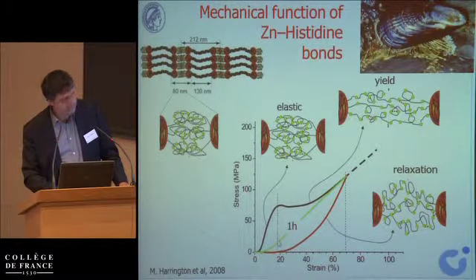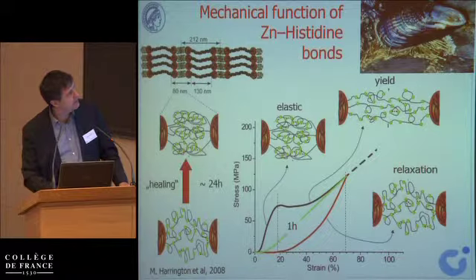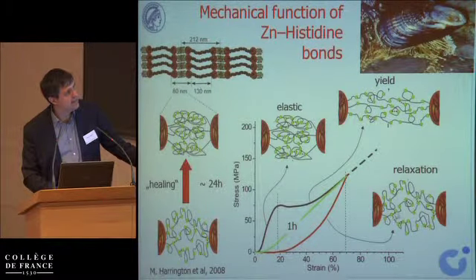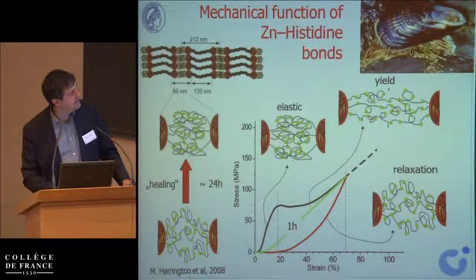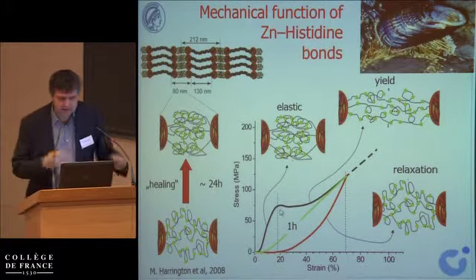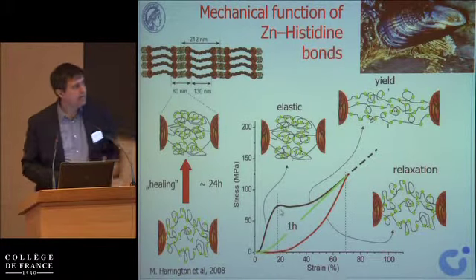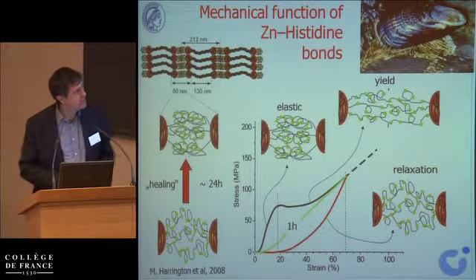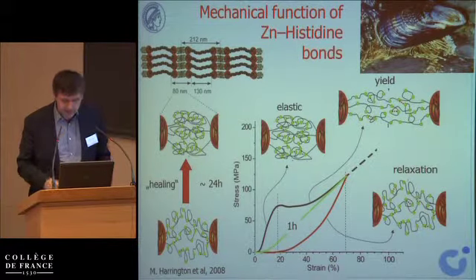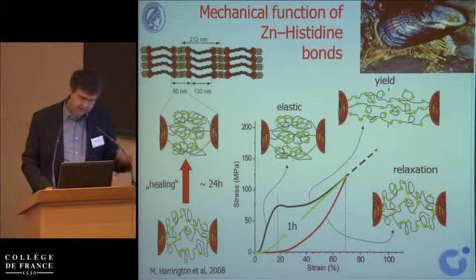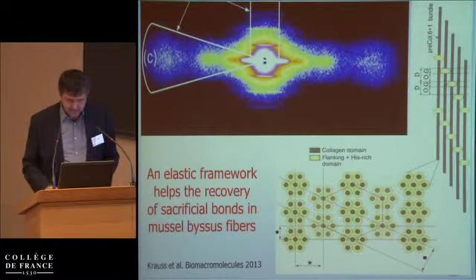But of course, if you wait an hour or if you wait 24 hours, what's going on is that these red bonds, since it's just a zinc ion that cross-links these two, the zinc ion finds again its histidines and it cross-links the whole system again, and then we can start all over. So every 24 hours there can be a very, very strong wave during the tide that tears the mussel away, and it can recover again within 24 hours, roughly speaking, to get back.